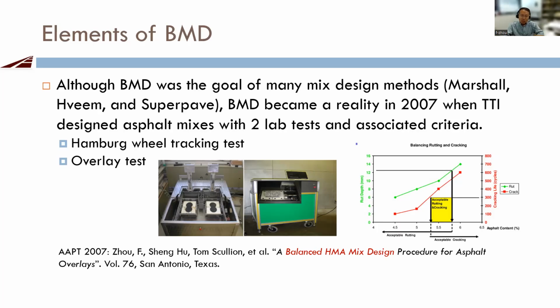Back then, we used two tests. One is the Hamburg wheel tracking test, and the other one is the Texas overlay tester. So these are the two test equipment shown here. And we came up with this balanced mix design concept. In order for a mix to perform well in the field, it must have adequate rutting resistance, moisture damage resistance, and cracking resistance. So simply put, this concept in one graph.